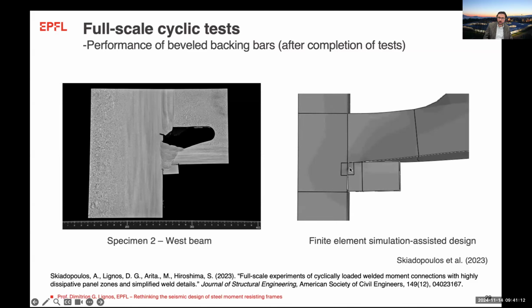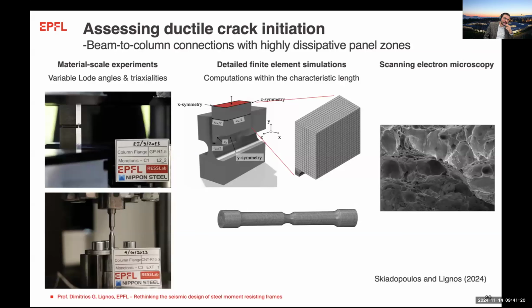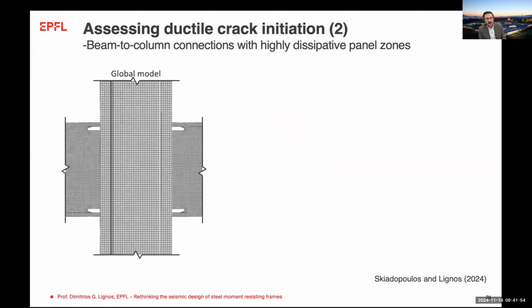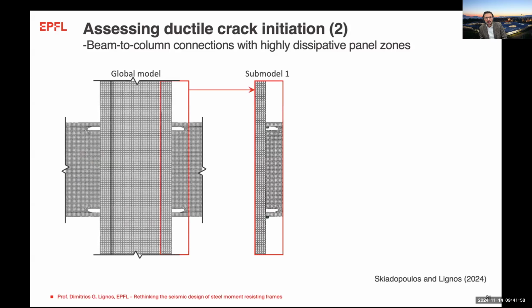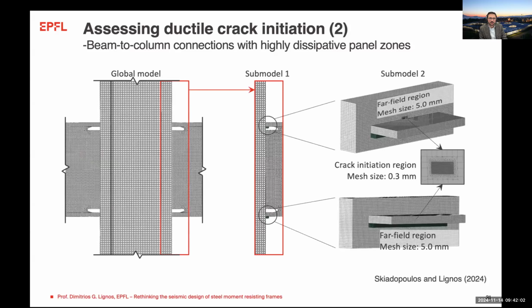Now, we've looked at this also with pretty serious continuum mechanics simulations where we assess the fracture potential by using micromechanics-based models to essentially find when ductile crack initiation starts, at what drift. And we did several material scale experiments with different geometries, as well as finite element analysis to kind of calibrate this test. And then by looking at scanning electron microscopy, we were able to essentially calibrate these models and essentially going back into geometries that are of interest to the designer, we were able to incorporate these micromechanics-based models and assess the fracture potential near the region where you have the bevel backing bar and near the region that we're usually afraid to have fracture.